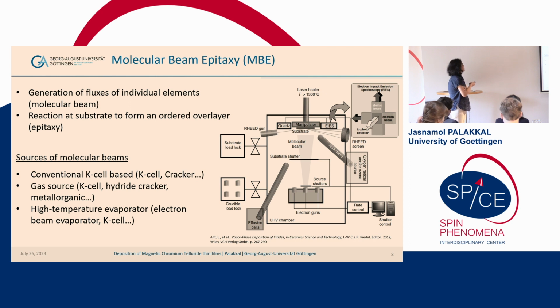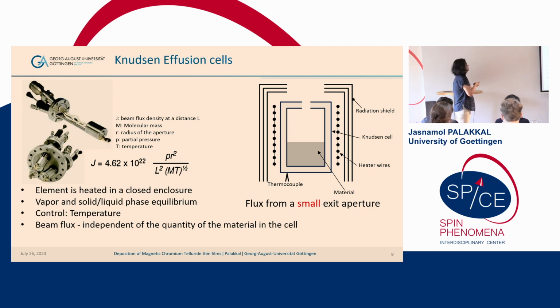So in a molecular beam epitaxy, the first step is to generate the fluxes of individual elements, and that's what we call molecular beam. And then the nucleation and the film growth happens at the surface of the substrate afterwards. We can have different sources of molecular beams, like Knudsen cell based effusion cells, or you can also use electron beam evaporation, and you can attach several sources of molecular beam in a MBE system, and you can get the deposition at the surface of the substrate. But we are usually choosing the source depending upon the element that you want to grow. Not all elements can be evaporated by using electron beam, but in that case you have to go for an effusion cell. So here this is the Knudsen effusion cell.